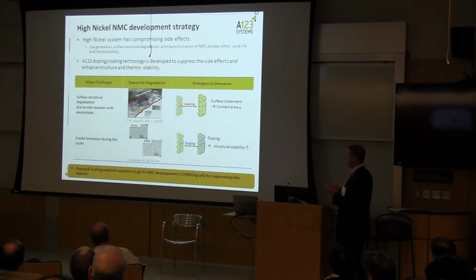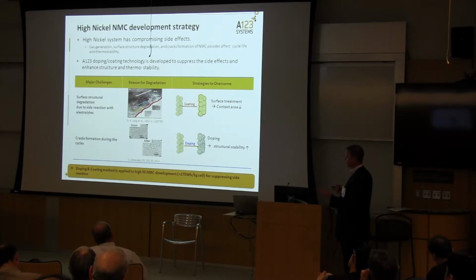One in the bulk, which is the cracking. And so we've come up with some interesting doping methodologies and elements that actually help reduce this cracking by relieving the stress during cycling. And this actually helps from an abuse standpoint, but it also helps in terms of the life of the structure.